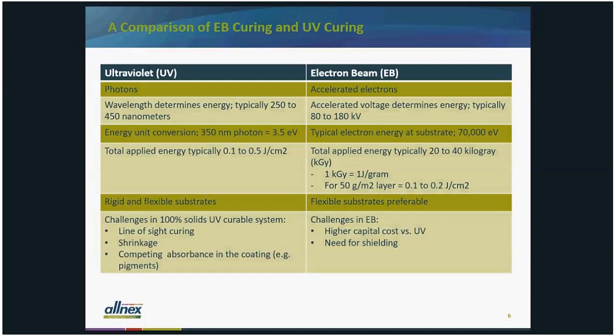Some of the challenges in 100 solids UV curable systems include the fact that it's a line of sight curing. If the area is not exposed to UV energy, then it's not going to cure. 100 solids energy curable systems have shrinkage associated with them. A good formulator knows how to accommodate that and work around that. And with UV, you get competing absorbance from different parts of the coating, especially pigments.